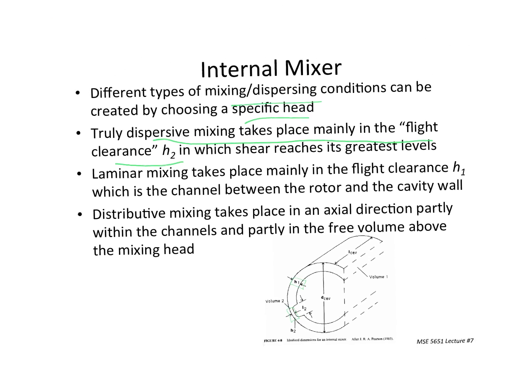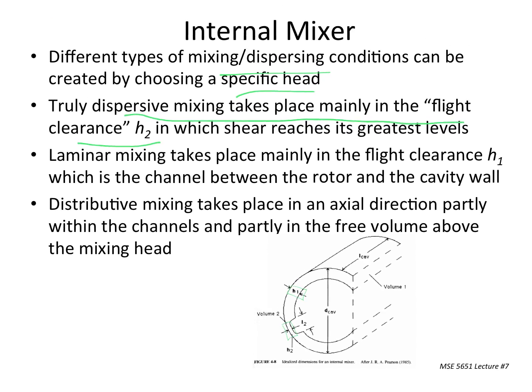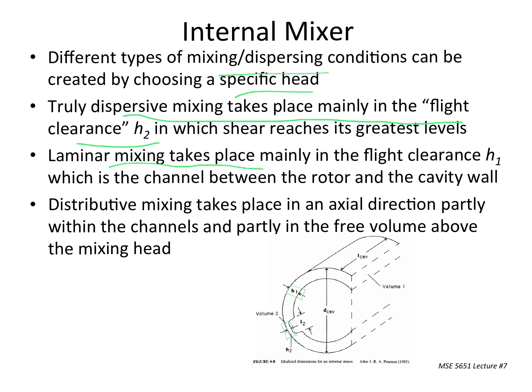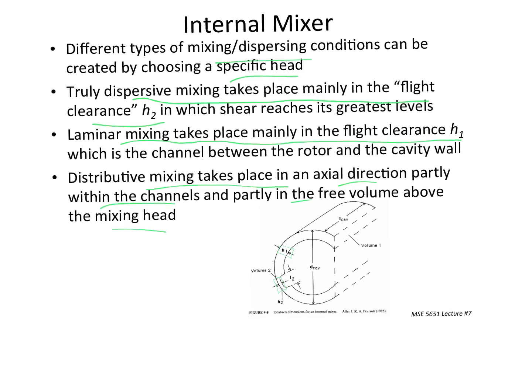And so the faster it spins, the shorter, smaller H2 is, the better off we are. Laminar mixing takes place mainly in flight clearance H1, which is just generalized mixing of everything inside this. Distributed mixing takes place in an axial direction, partly within the channels and partly in the free volume in the mixing head. So you break things down here at H2, and then H1 takes the products of what's broken down, mixes it with everything else, and then there's further mixing happening along the axial direction. So these are very efficient in terms of what they do in a small space.